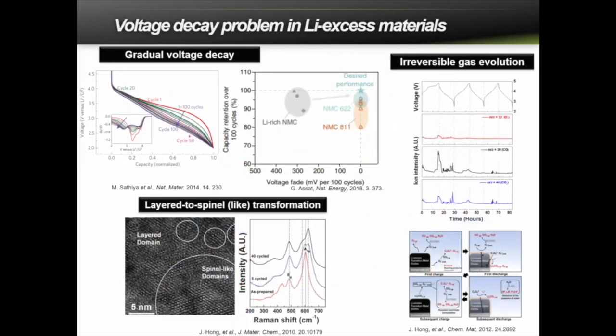Despite this promise of a higher energy density due to the additional anion redox reaction in this lithium excess material, there have been several critical problems that need to be resolved. One of them was the gradual voltage decay, which is typically observed when the lithium excess material is cycled multiple times as a cathode. It suffers from capacity fading, but also voltage fading over cycles. Considering the energy density is the product of the voltage and the capacity, the decay of both values makes the energy density decay double.